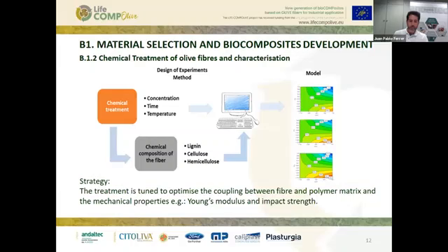This is very important for the next step, which was the optimization of the chemical treatment of that olive fiber. The idea is to have an optimum coupling between the fiber and the polymer matrix. And for having that, we tune the parameters such as the concentration of the reagent in the reactor, the time of reaction, and the temperature. And so we applied a mathematical model in order to have the optimum parameters for the chemical treatment.